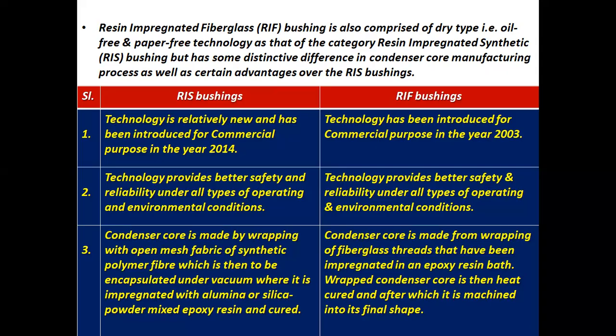But for RIF bushings, the condenser core is made from wrapping of fiberglass thread that has been impregnated in an epoxy resin bath. The wrapped condenser core is then heat cured, after which it is machined into its final shape. The only difference is that here an epoxy resin bath is used, but in the case of RIS bushing, it is alumina or silica powder mixed epoxy resin and cured.